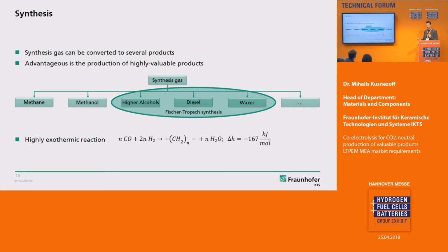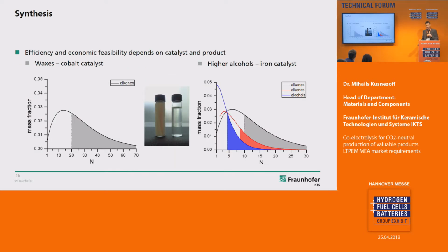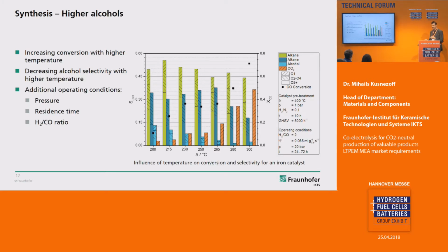The problem is, by conversion, that it is a highly exothermal reaction, and we should manage the heat flows in the system. But first, we should start with our catalysts, because you should have a system which can very selectively produce your chemicals. Normally, you get a spectrum of chemicals, but you want to have one special chemical. And we are in the high temperature region. It means that we try to use iron-based catalysts. Here is a picture showing the selectivity of iron-based catalysts at different temperatures. And we see that 200 degrees C is somehow the optimum to get the selectivity for alcohols.